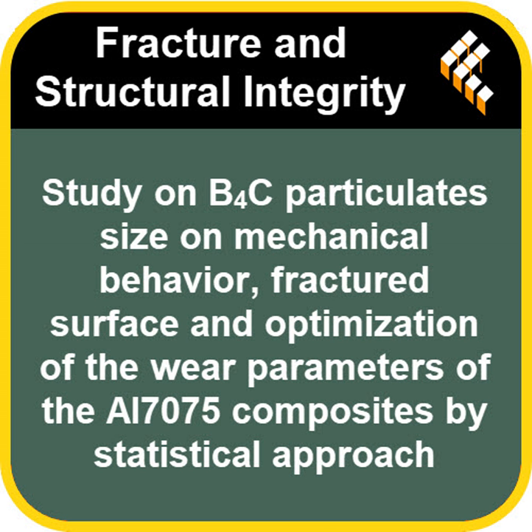the nano ones. Really? Why would the bigger particles be better at that specific thing? The researchers think it's down to wettability. Basically, the microparticles integrate a bit more easily into the molten metal. Nanoparticles have very high surface tension, which can make them harder to disperse perfectly and integrate smoothly compared to the micro ones in that specific regard. Oh, interesting nuance.